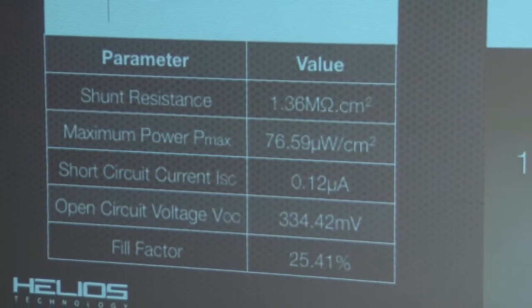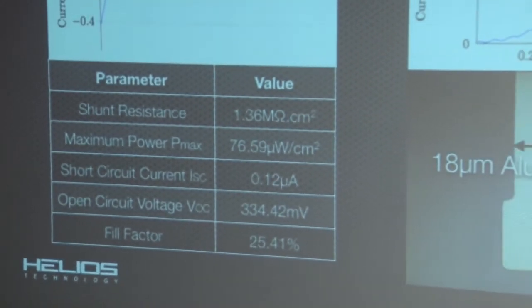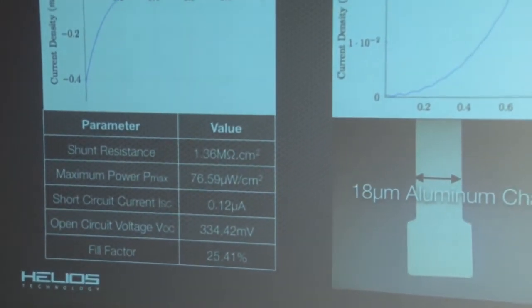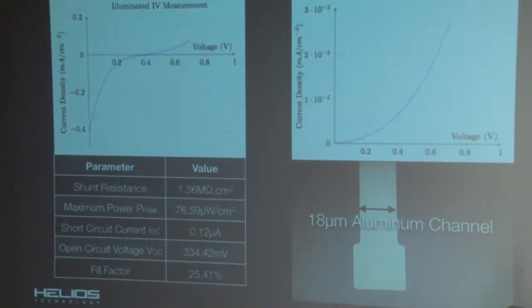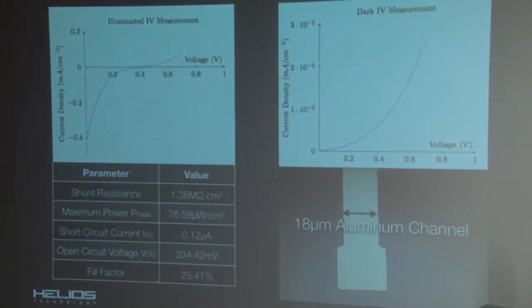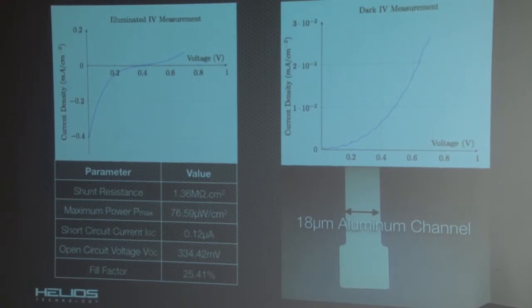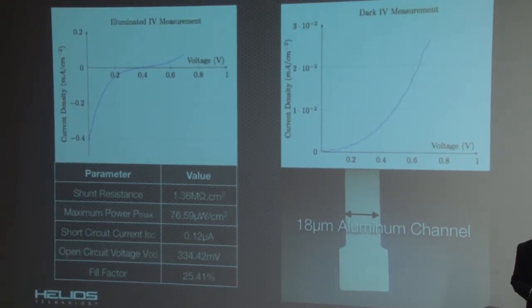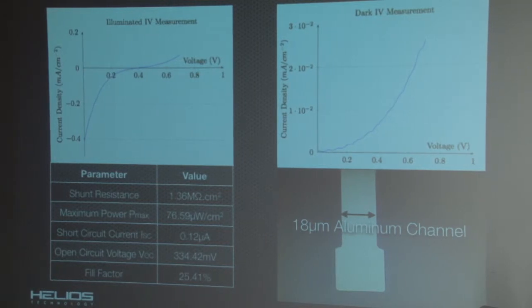The biggest downfall for this prototype was that we got a very small short circuit current, about 0.12 microamps. And we got about 0.4 volts as open circuit voltage and a 26% fill factor, or 25% fill factor, which is again as expected.